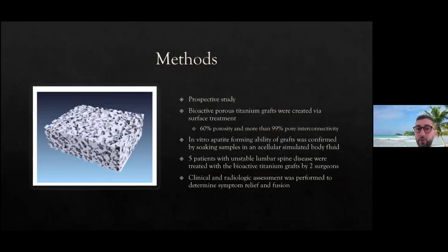And so what they did is they created these bioactive porous titanium grafts. I put a picture here from the study. They have about 60% porosity, 99% pore interconnectivity, which apparently is important for bony formation. And they treated them to make them bioactive, and it's basically a chemical processing of the graft. And they confirmed that they truly were bioactive by doing in vitro studies in an acellular simulated body fluid.